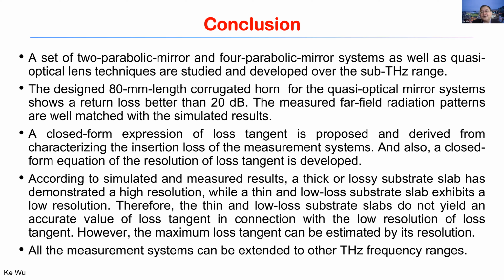At the same time, we have shown through the measurement and simulated results that the system is very robust. We can also see that the quasi-optical mirror system and the quasi-optical lens system both provide very accurate results, even in a very dynamic range environment. So this system can of course be extended to higher terahertz frequency bands. So that's my talk.